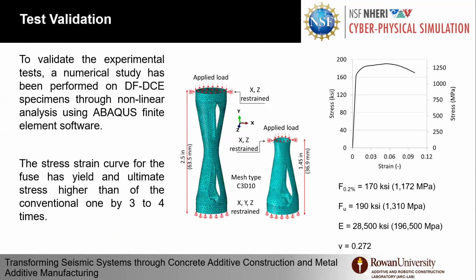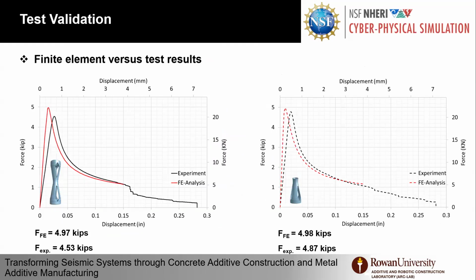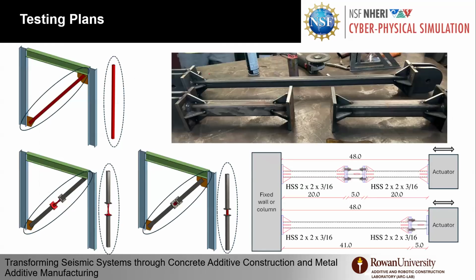So we did a lot of numerical simulation using Abaqus. We're still on the verification side of it. This is the blind prediction before we start doing the iteration. We get the behavior, but the numerical models are still stiffer. There is a lot we're trying to do with the digital image correlation data that we gathered during the test to actually model the material, because what we used is just a stress-strain curve for this material.